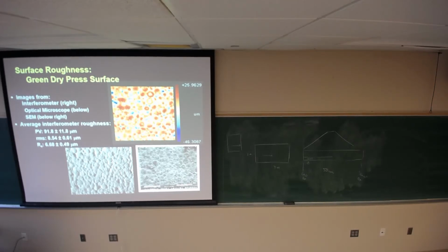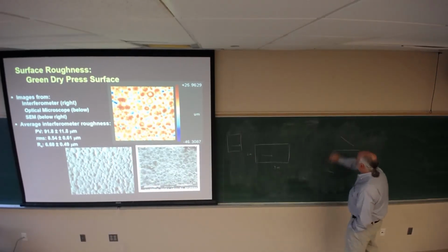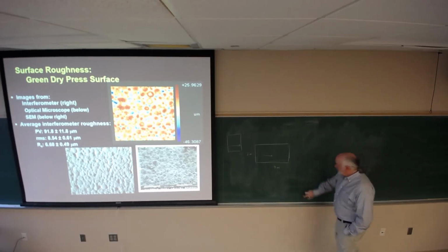Now, this, in my opinion, is a game changer. You see it in other cases too, this idea of continuous sintering and the stresses involved for shrinkage. This further argues that all of our problems associated with cracking and shrinkage, and cracking due to shrinkage during firing, have only to do with processing and nothing to do with firing. In my opinion, we need to reevaluate everything we know about sintering in the context of this and defect generation during firing, because they can do this. We have a really interesting problem that we think is true. This 50-minute thing is the other. So we're trying to figure out how to measure it. We think we can do it.